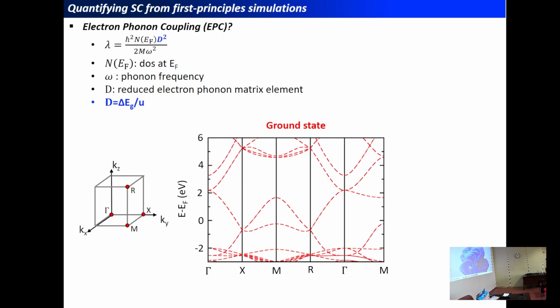So now with the simulation, the question is how can we estimate the superconducting properties? So superconductivity is related to an electron-phonon coupling in which we will try to estimate how the electronic structure is affected by the presence of a phonon in the material. And so what we want to compute is the electron-phonon coupling lambda. It quantifies the strength of the coupling between the electron and the phonon. And so it depends on 3 key parameters. So N(F) is the density of states at the Fermi level. So the higher the density of states, of course, the higher will be the electron-phonon coupling. But it also depends on the frequency of the phonon mode that we will look at, and on the reduced electron-phonon coupling matrix element, which will quantify what's happening in the band structure in the presence of a displacement associated with the lattice vibration.